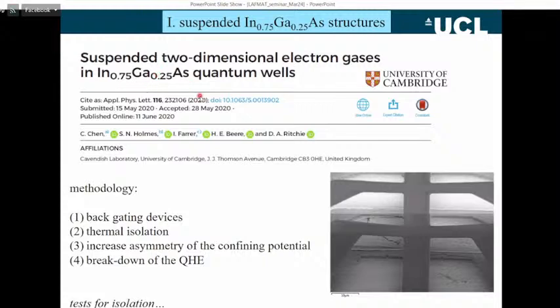So just before COVID came, we got this work. And what we published in this work was, in fact, you can see an SEM image here. So this is an image of the device. This is the channel. This is the conducting channel. These are arms, potential arms for measuring voltages. And it's come up above the substrate. We've etched away underneath the substrate.